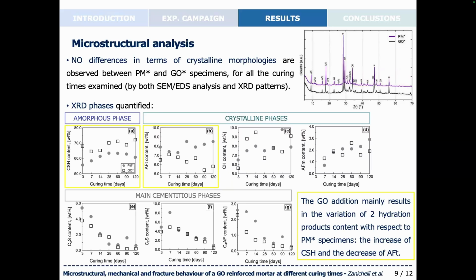In particular, the amorphous phase content increases for both specimen types, but the increase is more remarkable for the GO* specimens, and also the values obtained for GO* specimens are always greater than the corresponding ones for PM* specimens. And also, if we look at the CSH content for PM* specimens, we can see that it increases up to 14 days, and then it remains quite stable up to 120 days.